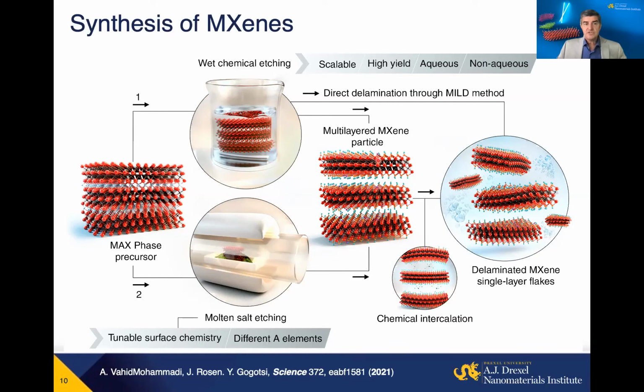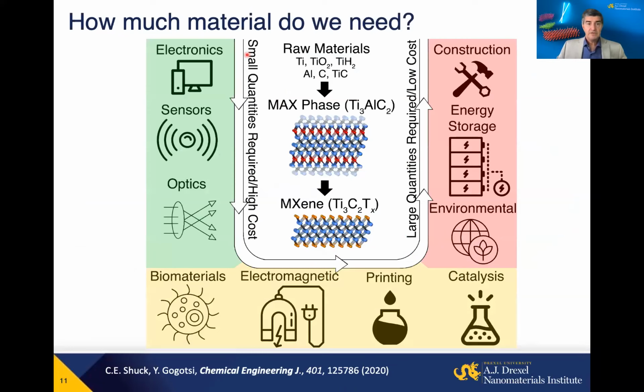but also strengths. So after etching, after removing the A element or other binding group of elements, we end up with multilayer structures, which are now bonded by weak van der Waals forces or by hydrogen bonds, and they can be delaminated and intercalated the same way as other materials here. What is important? If you look at the majority of materials, except graphene, boron nitride, moly disulfide, tungsten disulfide, all other nanomaterials people talk about are produced in extremely small amounts.